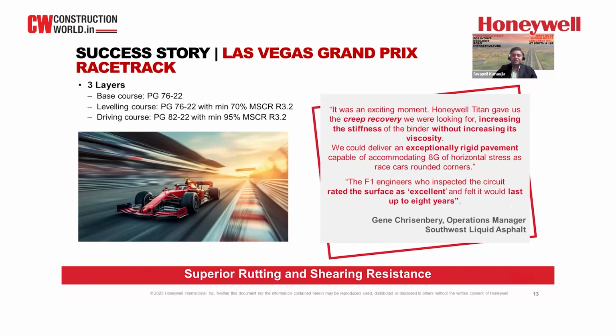Here the problem statement was to lay the track with higher PMB grades, due to which the viscosity was shooting up on the higher side, and the customer was also failing to meet the creep recovery as per the standards. The approach the team followed was some in-house lab work, which resulted in an optimized dosage of hybrid formulation. This helped achieve the required specs while keeping the viscosity within limits, which further helped in ease of paving and enhanced workability at the site. Can you move to the next slide?